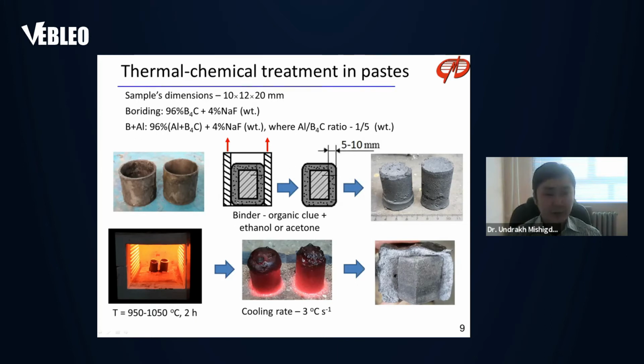Treatment powder was mixed with organic glue and ethanol until achieving a pasty condition. Then the sample and treatment paste were placed in cylindrical molds. After a while, the molds were removed and the obtained briquettes were dried.